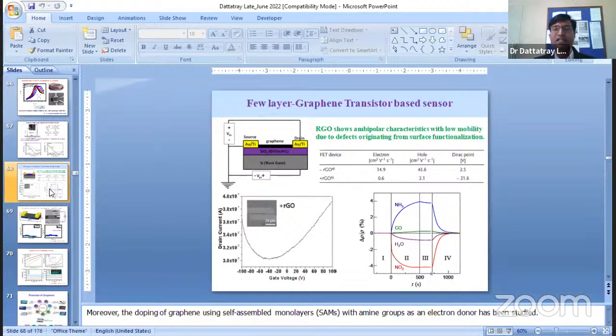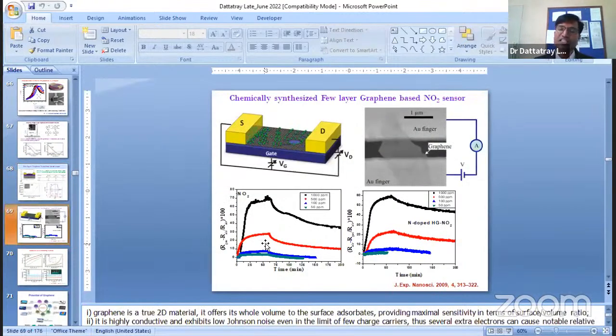Can you make graphene a sensor? Again, because there is no band gap, sensitivity is very good, excellent. Selectivity is also good. But there is the response and recovery. Response is also good, but recovery is difficult, because the binding of molecules on the graphene sheet is so high that it is difficult to remove these adsorbed molecules. So we have to provide large energy, an external energy supply, so that you can take out all the molecules bound on the surface, so that your recovery time will be much faster.